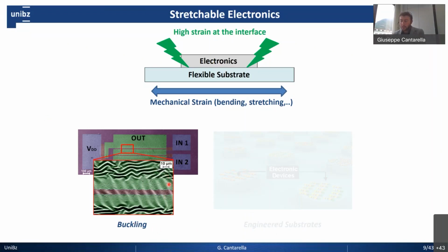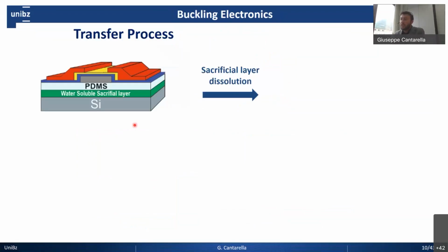As you can see here, the idea was to create out-of-plane wrinkles in the layers of my electronics, in a way that whenever I apply a certain mechanical strain, for example bending or stretching, I am not stressing the electronics, the device itself, but rather reflattening these wrinkles. The way we achieved this was using a transfer release process.